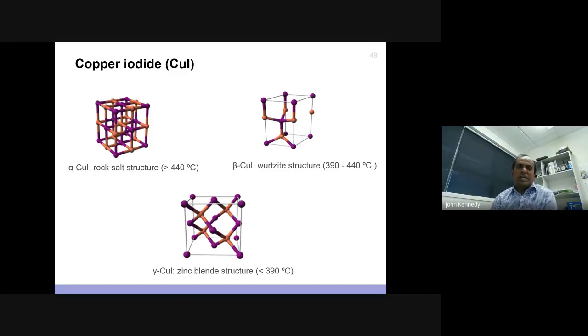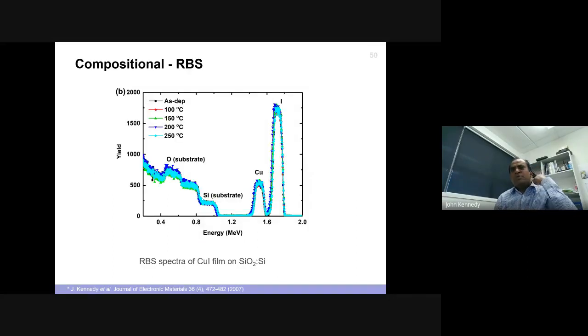So the literature clearly says gamma phase copper iodide is what you need in order to have a transparent and thermoelectric material as well. So we made films again as usual. We always make thin films. We do RBS to measure the compositions, as deposited and after annealing.